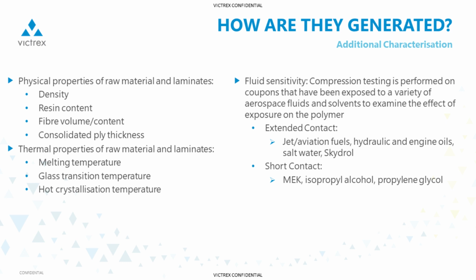In addition to these physical properties, fluid sensitivity is also generally captured, typically using compression testing, and can include specimens that have had extended contact with jet or aviation fuels, hydraulic and engine oils, salt water, skydrol, de-icer fluid, short contact with a variety of solvents such as MEK or IPA or propylene glycol. And of course, this list is also not exhaustive if there's something more specialized that needs to be explored.